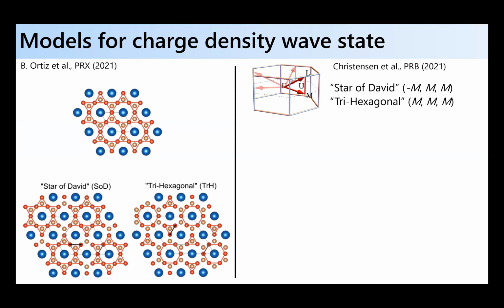All right, so if you think about the kagome lattice, this is just looking down the C-axis of these 135 compounds. This is in the high temperature phase. And so the kagome net itself is energetically favored from DFT to either breathe into a Star of David kind of distortion where it breaks up into these Star of David units, or to breathe into the so-called trihexagonal distortion where the kagome net breaks up into these hexagons and triangles. Okay, and the two distortions are related to one another.